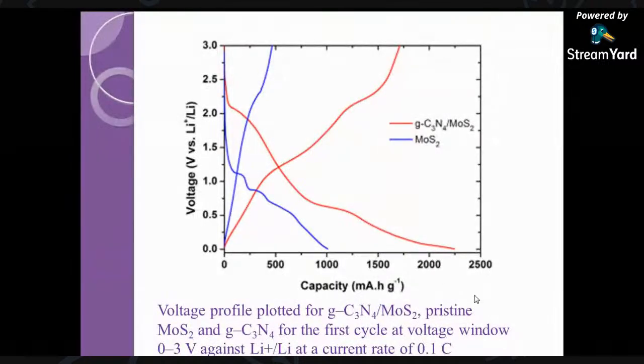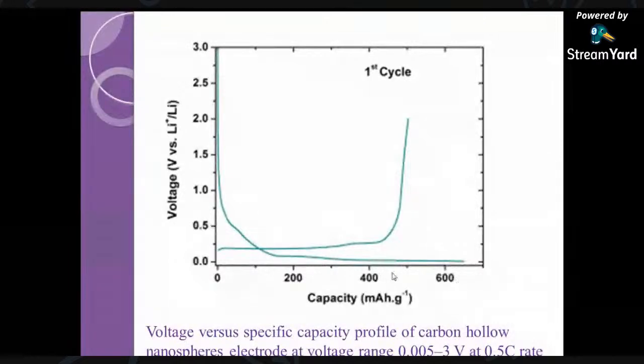Then the graphitic carbon that we have created before with MoS2 has given tremendous performance in the application of lithium-ion batteries, with a good discharge capacity greater than 2000 when compared to MoS2. So this is MoS2, and this graphitic carbon MoS2 structure gives you more capacity because of the presence of graphitic carbon nitride. Then when we go to the application for carbon nanospheres, you can see the charge discharge cycle for battery applications using carbon nanosphere electrodes. A good capacity has been achieved, which is greater than the graphite.